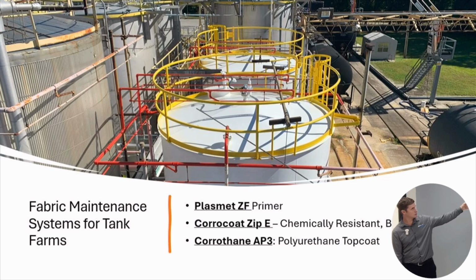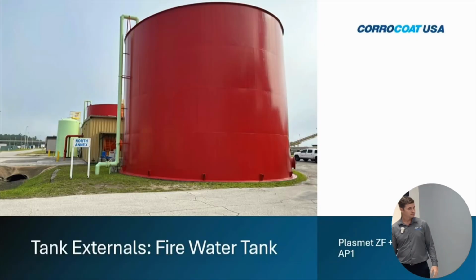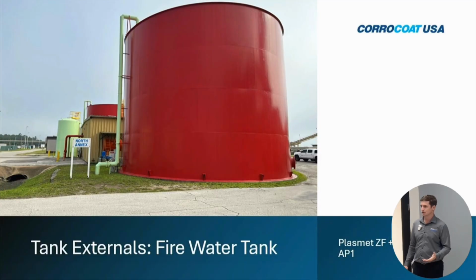In situations like this, a petrochemical plant, they were worried about gases and gas releases, so they didn't want just a corrosion barrier. They wanted a chemical-resistant corrosion barrier as well, worried about SO2. So we used the ZF primer so that we didn't have to abrasive blast, which was frowned upon in that area. Then we went on with Corrocoat Zip E, which is more chemically resistant. And then we have a Corrothane AP3 top coat as well. Same concept with firewater tanks. It's a nice, pretty red picture, fitting at Qualitech.